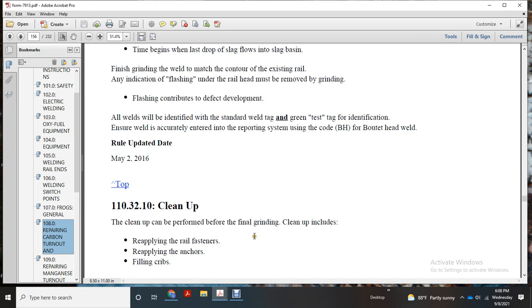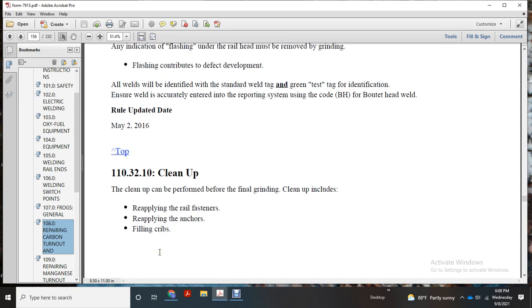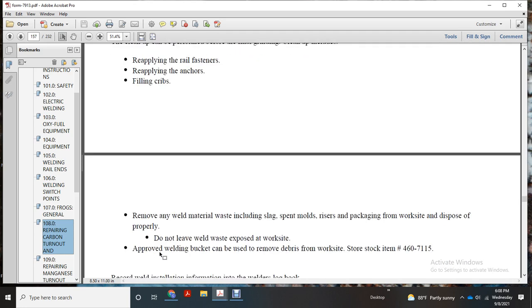Cleanup is performed before final grinding. Cleanup includes reapplying rail fasteners, reapplying the anchors, and filling the cribs, and removing any weld material waste, including slag, spent molds, risers, and packing, with proper disposal of the waste. Do not leave the weld exposed to the worksite. An approved welding bucket can be used to remove the debris from the worksite, stock item 460-7115.